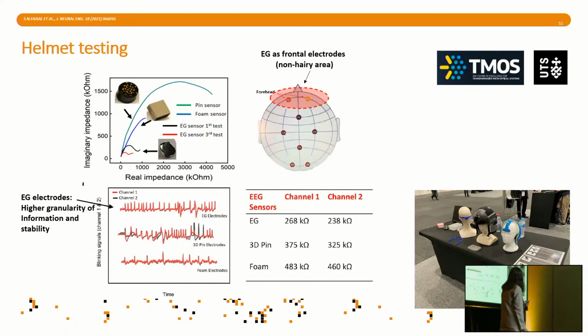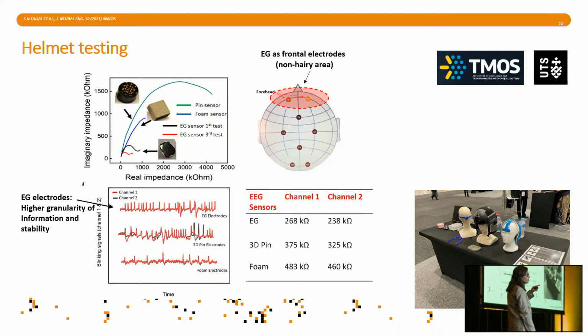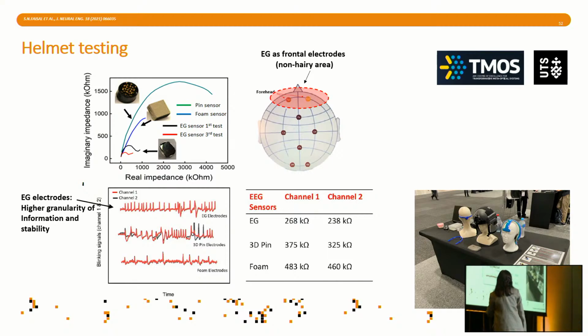And so this is really helping us to achieve stable, very stable performance. We kept it for the whole lockdown down in Sydney. We kept the sensors in high saline solution. We maybe lost 1%. It's incredibly resilient in terms of adhesion, but also in terms of electrical behavior, which is something that you can't achieve with this type of sensors.